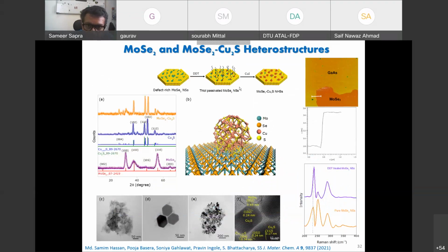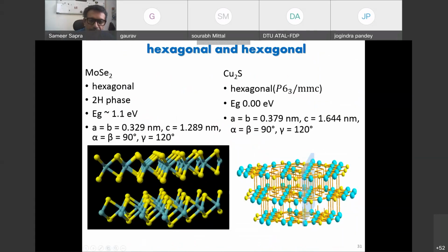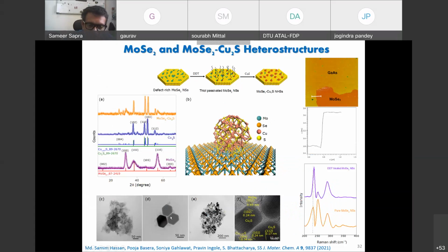The way to make these heterostructures is essentially that you take molybdenum selenide nanosheets, and since you have a lot of defects, which are selenium vacancies, you put some thiol, dodecanethiol, DDT, on top of it. This dodecanethiol goes and sticks to molybdenum because molybdenum is hungry for the chalcogen, and thiol is sulfur. Then you put another one, cuprous iodide, which is also hungry for thiols. So this goes and forms these islands of cuprous sulfide on top. If you look at the TEM, this is MoSe2, and this is cuprous sulfide synthesized separately. But when you do it on top, then you get these kinds of heterostructured materials, all well characterized.